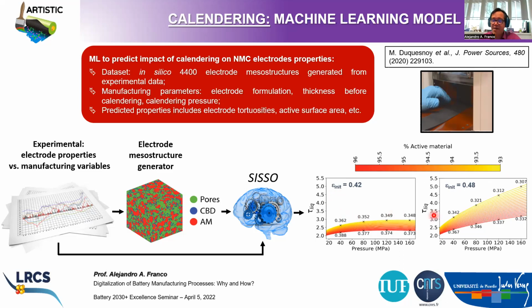And here you see that there is a very strong sensitivity, right, of this tortuosity factor evolution with the calendering pressure, because of course, when you increase the pressure upon calendering, the tortuosity factor increases. This is something that we have already studied before in one of my previous slides. But also what you see is that the degree of increase of this tortuosity factor depends on the electrode formulation, but also depends on the porosity that you have before the calendering, right? So this once again shows the complex interdependency between parameters, because here I'm talking about calendering pressure, formulation and porosity of the electrode before calendering, and how these parameters will impact the tortuosity factor of your electrode. Machine learning is a wonderful tool to unravel these correlations, right? And establishing this correlation just by hand, analyzing the data set that you have, for example, in an Excel file by hand, would be very challenging, right?